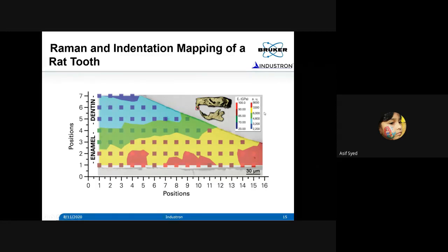Whereas in dentin, the mineral content is low, you can see that the intensity is low, and you can also see the modulus is low. So now we are able to correlate the mineral content to the measured modulus. This is how we can progress in our findings. Okay, now we know there is a variation in mechanical property. Now we know why there is a variation, because of the mineral content. So we can tie the mineral content to the mechanical property. This is how we progress.